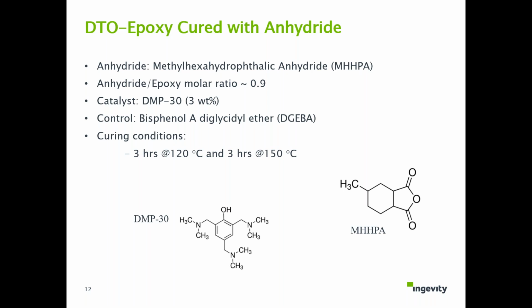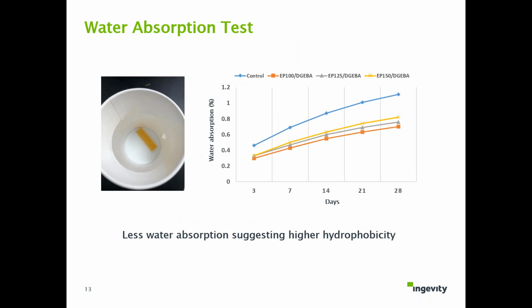Again, we're using EPON 828, a bisphenol epoxy, as benchmark only for comparison, to see how comfortable we feel about our DTO-epoxy performance. The curing condition is 3 hours at 120 C followed by 3 hours post-cure at 150 C. Water absorption is always an important property for epoxy applications, because when epoxy resins are cured they generate secondary hydroxyl groups, which can potentially pick up water. We did this water absorption test by immersion test, from 3 days up to 4 weeks.